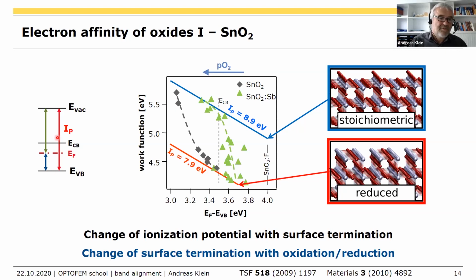And the sum of the two is the ionization energy, or you can also subtract the band gap and you get the electron affinity. And now by looking at this, you see that there are some samples which have a high Fermi energy. This is more under reducing conditions. Your ionization potential is something like 8 eV. But if your samples are more oxidized, your ionization potential is 9 eV. And that is due to the different surface terminations of the tin dioxide.